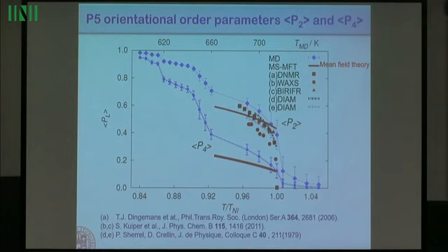And this is very disappointing, and shows that really, even for a very well-defined system, nobody in the world at the moment can calculate things like transition temperature, which are apparently simple, but for the theoretician they are not, because they are a derivative of a two-particle correlation function, which involves four-particle correlation, which is tricky. But anyway, we can get it within a few degrees, and we compare favorably with a variety of experiments: magnetic resonance, wide-angle scattering, birefringence, diamagnetic. This is not the place to give details.